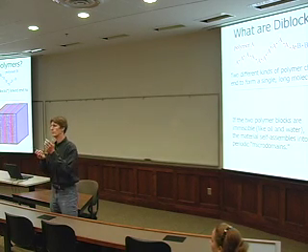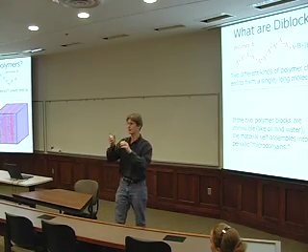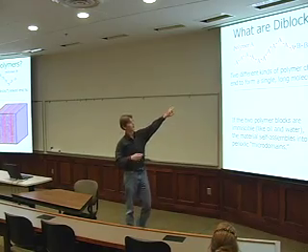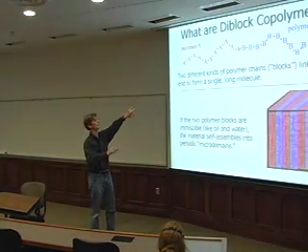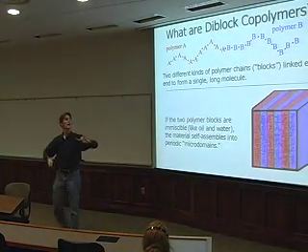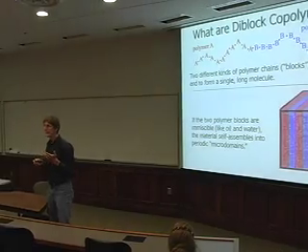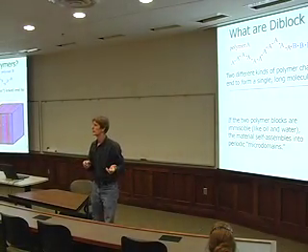And of course, you know what happens with oil and water, or oil and vinegar in a salad dressing. You shake it up, and of course it starts to spread apart with the oil on top. If you think about it, what these molecules are like is, if you could separate all of the B chains from the A chains and mix them together, they'd separate like a salad dressing. But notice that in this case, the two species are actually linked together as part of the same molecule. And that means that they can't separate macroscopically, like the salad dressing does.